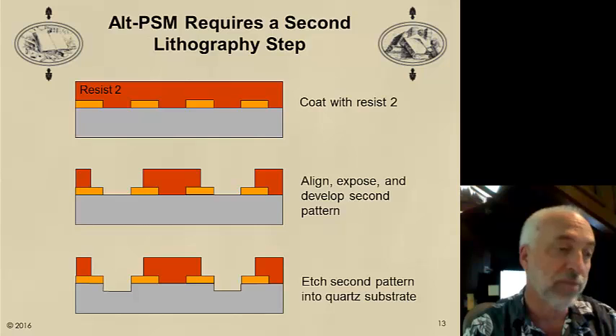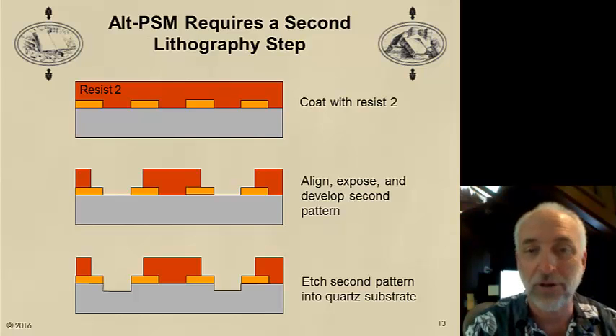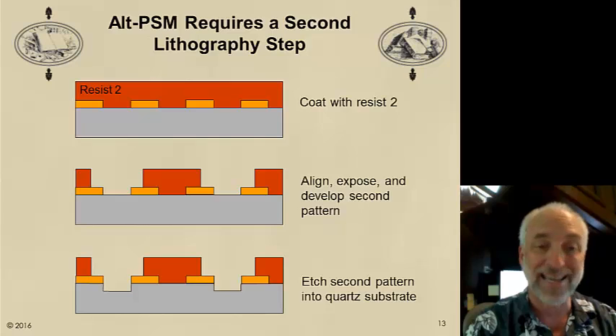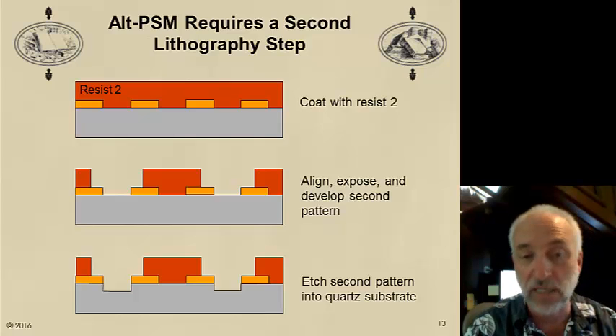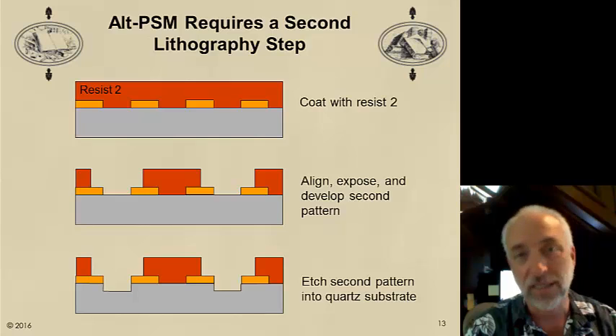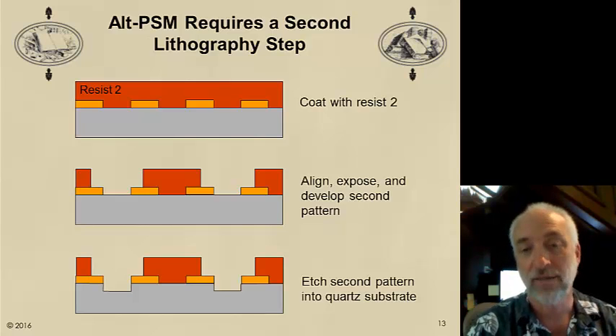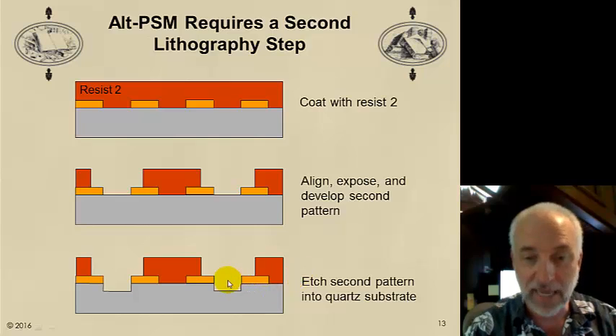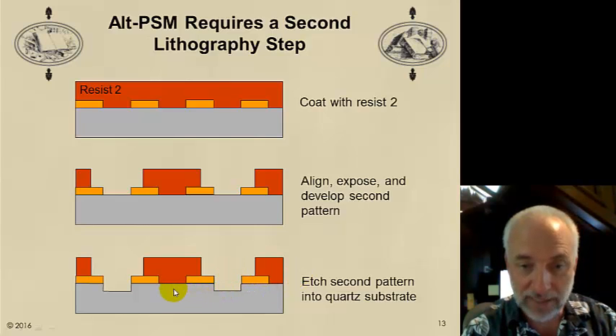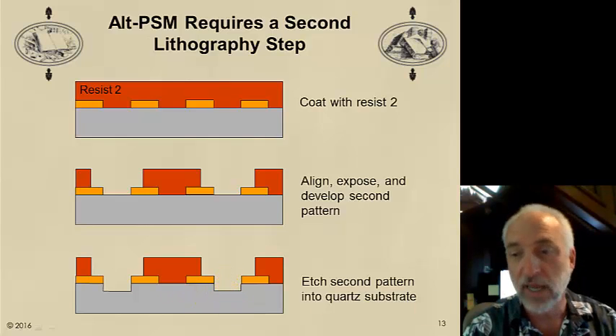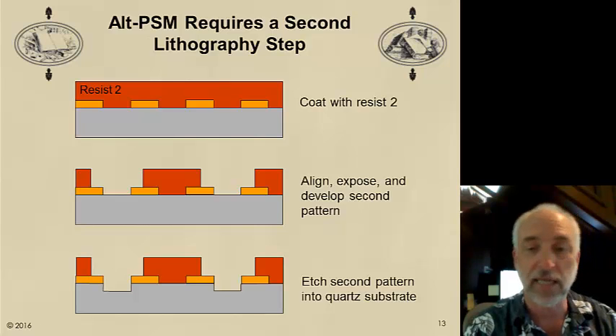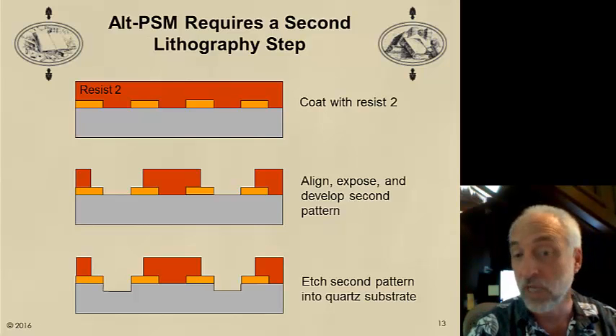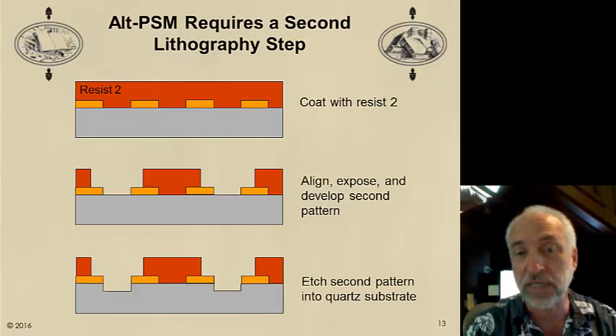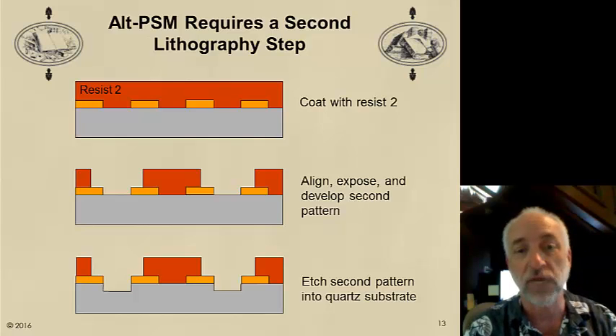Now, in the previous slides when I talked about how alternating phase shifting masks worked, I showed an extra thickness of glass being deposited. It's easier to make the mask if you etch away the quartz. This does the same thing in the phase shifting principle. We have a difference in the thickness of glass in one region compared to the thickness of glass in another region. And taking away glass is the same as adding glass. You can achieve the same phase shift. We just need to make sure that we etch it at the specific thickness, the specific depth of the etch that we need to give us that 180 degree phase shift.